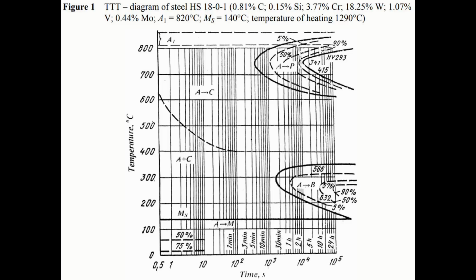Well, here is a TTT diagram for a T1 high-speed steel. And one thing you notice right off the bat is that the transformation times for Bainite are extremely long. Like if we hold at 250 Celsius, that's around 500 degrees Fahrenheit, to get to the 90% transform line, we are out at 24 hours, which is quite a long time. I don't know if I want to sit around waiting that long.